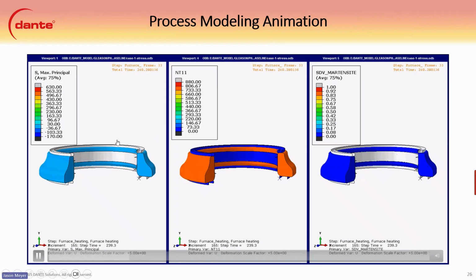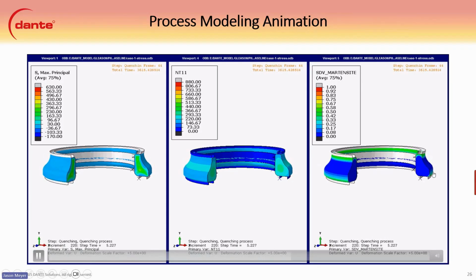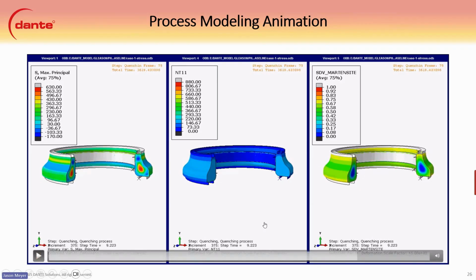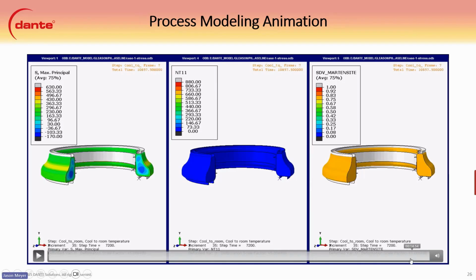So with process modeling, we have the maximum principal stress shown in the contour here. We have the temperature of the part. You can see it being quenched right now. And then we have the martensite transformation happening right there, the volume fraction. The important and critical part of this is right about here. When the martensite transformation is pretty much complete on the outside, the core begins to transform. You can see the more green color here, whereas the outside is all as-quenched martensite. And when this begins to transform, it's being held in by the pads on the inside, the top, and the bottom. And really the only way for it to go is out this way with the volume expansion. And you can see that results in a very high peak stress around that region where they're showing the cracks.